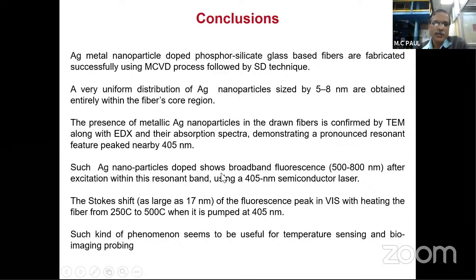This silver nanoparticle shows broadband fluorescence from 500 to 800 nanometer after excitation within its resonant band using a 405 nanometer source. And a shift of the fluorescence peak occurs in the visible after heating from 250 to 500 degrees centigrade. Such phenomena will be useful for temperature sensing and bioimaging purposes.